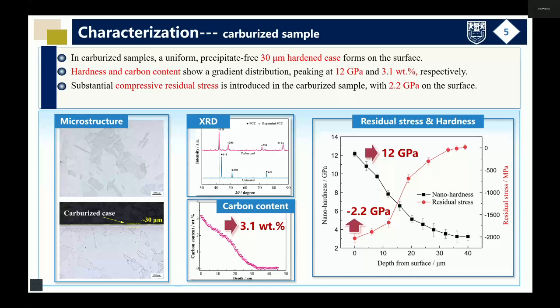The metallographic image shows that in the carburized sample, a uniform precipitate-free, 30 micrometer hardened case forms on the surface. The hardness and the carbon content show a gradient distribution, peaking at 12 GPa and 3.1 weight% respectively. Substantial compressive residual stress is introduced in the carburized sample, with 2.2 GPa on the surface.